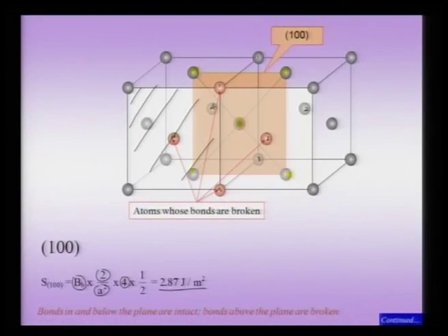No, surface energy is always higher. The reference point for surface energy is the bulk. The reference point for surface energy is not the vacuum. So, this is a very important point you raised. Now, is the surface in a higher state of energy with respect to, say, an isolated atom sitting in vacuum? Obviously, the surface energy is not that reference state. It is assuming that the crystalline bonded state is my reference state. And therefore, the surface energy is calculated with respect to the perfectly bonded crystalline state.